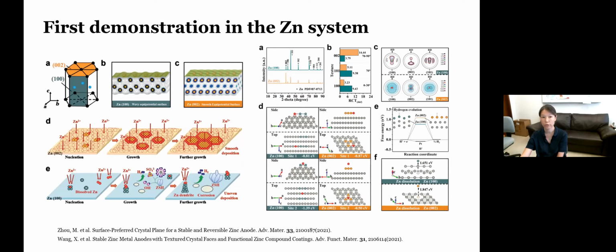The first demonstration experimentally was actually not coming from the alkali metals, but from the zinc system, which takes a hexagonal structure. Up to date, there are actually quite a number of works on the preferential texturing of the zinc system, but the earlier and representative work was done by Liang's group. They did show there are a number of benefits associated with the zinc 001 orientation, which is the basal plane of the hexagonal zinc. And these benefits include reduced parasitic reactions, such as the hydrogen evolution, improved corrosion resistance, and most importantly, suppression of the zinc dendrite growth.